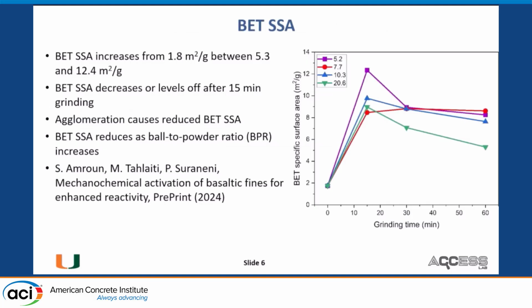Okay, so some results. We had a basaltic fine that we took. This material was very, very inert. And we said, hey, we are going to mechanochemically activate it. We varied the BPR, which is the ball to powder ratio, so just the amount of charge versus the amount of material. And we also varied the grinding time.